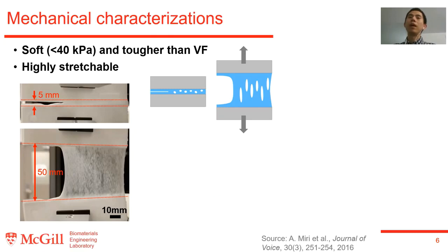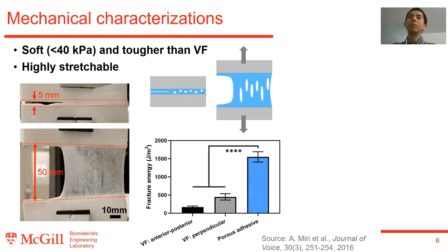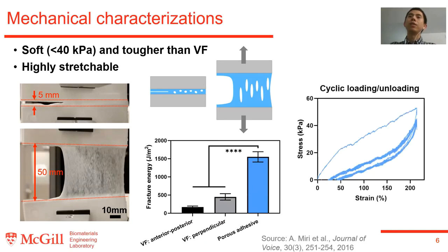Our porous adhesive has a much higher toughness compared to the porcine vocal fold tissues. It means that, assuming the adhesion is good, our adhesive will not fail before the vocal fold ruptures in some extreme cases. And when you look at the cyclic loading and unloading curves, you can see that the stiffness of our adhesive is within 30 to 40 kilopascal.